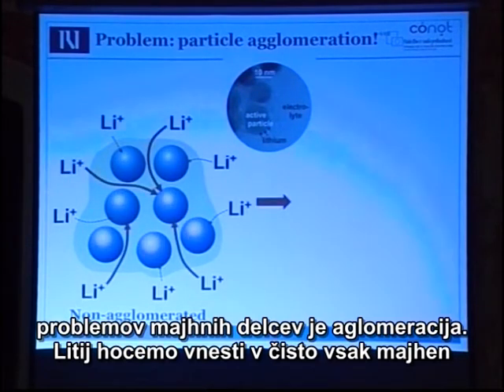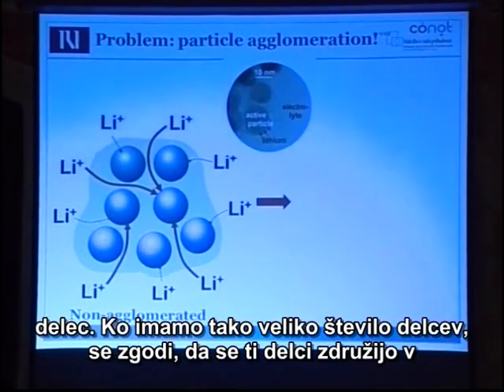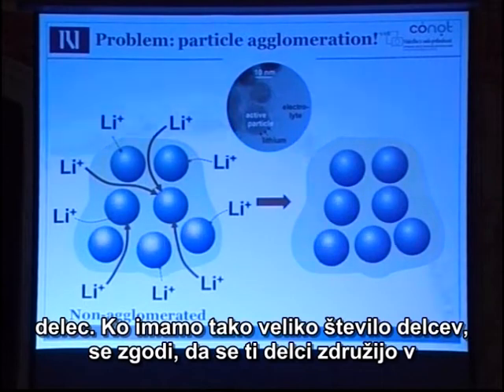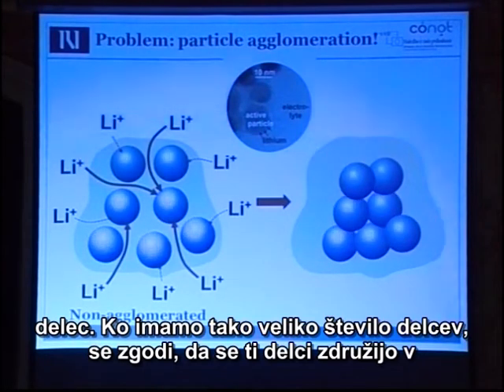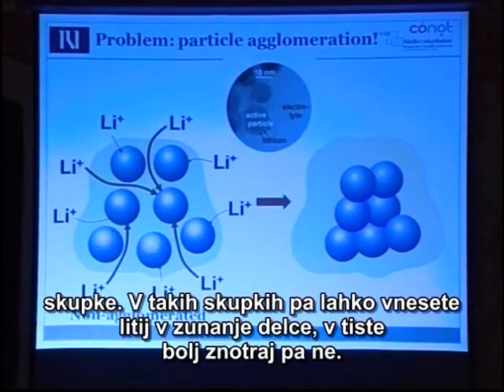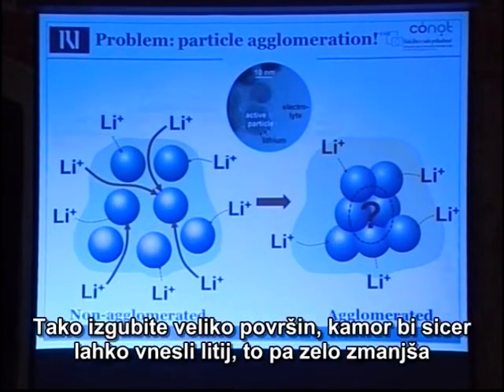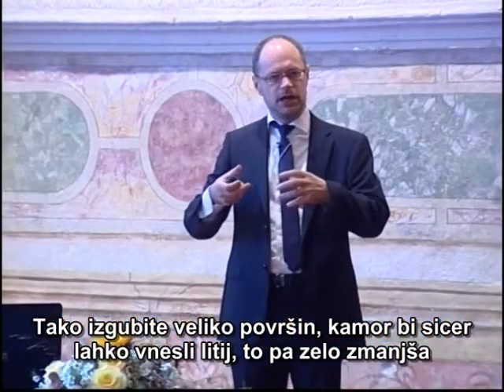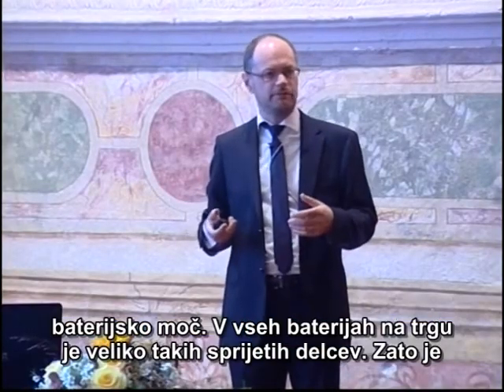What you want to have is putting lithium everywhere in each of your particles. Of course, what happens when you have a lot of particles is this kind of agglomeration. So particles will agglomerate. You will be able to put lithium from outside, but not from inside. So you lose a lot of surface area by this agglomeration, and you decrease your power very much.